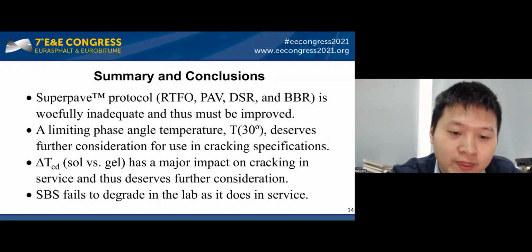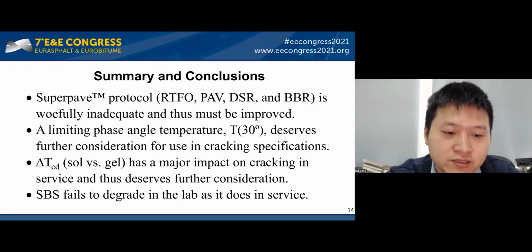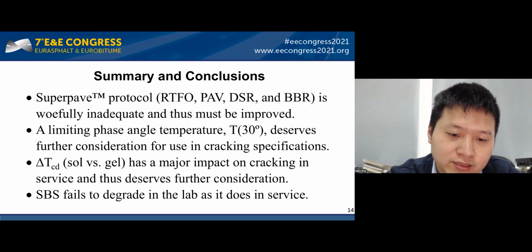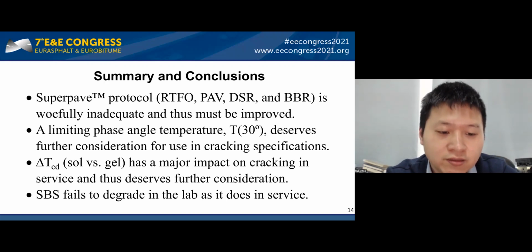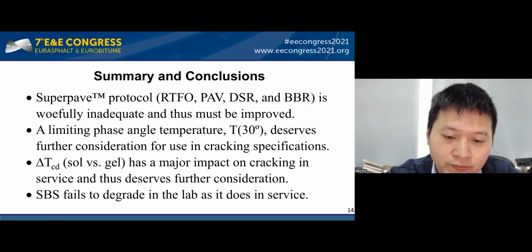In summary, the Superpave protocol that uses RTFO, PAV, DSR, and BBR methods is woefully inadequate and thus must be improved. The limiting phase angle temperature needs more attention, as it provides grades that are much better than those obtained by the regular BBR, are much more precise than those obtained by the extended BBR that uses 72 hours of conditioning, and are as accurate or more accurate than extended BBR grades. The delta TCD provides a handle on the shape of the rheological master curve, or the sol versus gel type, and as such is a good complement to the limiting phase angle temperature.